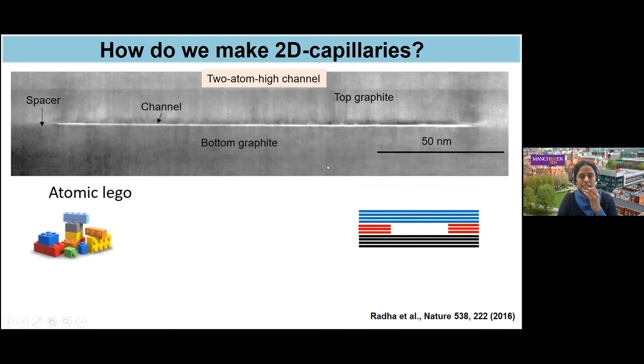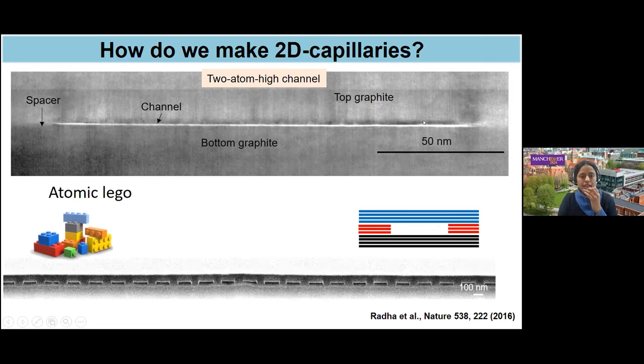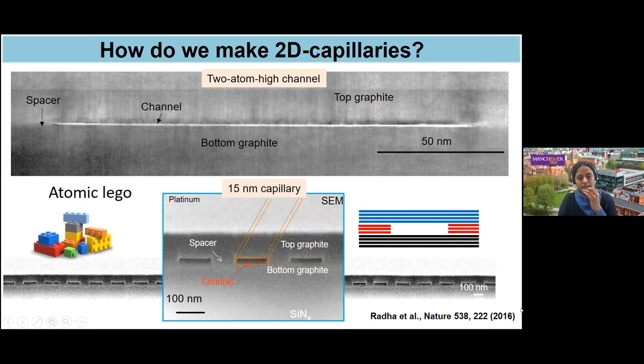Is it really possible to make such a capillary? Seeing is believing — this is a transmission electron microscopy image of one such capillary, which is a sandwich of three graphite layers: top graphite, bottom graphite, and a spacer which is two-layer graphene. This bright white empty space seen here is equivalent to the height of the spacer. We can make capillaries ranging from one layer of graphene thickness to a few tens of nanometers tall. The capillaries are quite rectangular with no sagging on the top into the channel.